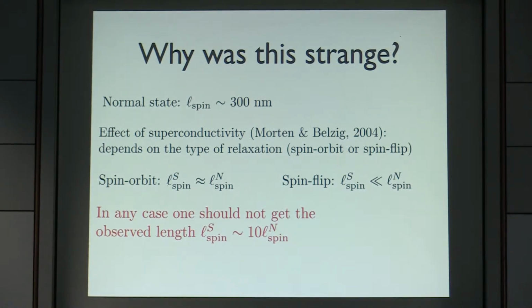Just to specify, the spin flip is the flipping of the spin by a magnetic impurity. Exactly. And spin orbit is the precession. This is, let's say, the isotropic spin orbit term that is usually present in any material. So, for example, in aluminum, it's the spin flip that matters, and in niobium, which is a heavier material, the spin orbit is usually the dominant one.